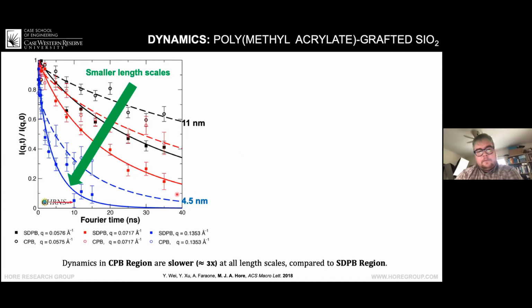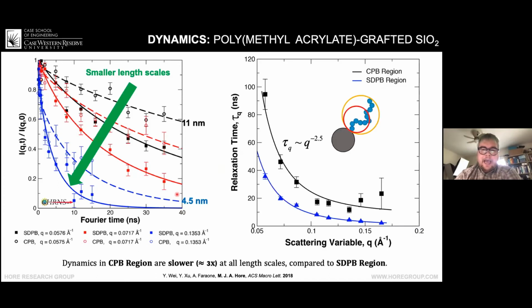So we can fit these data and we can tabulate what we observe, and we find that the relaxation times decay as Q to the minus 2.5, and all that's saying is that we get good agreement with the Zimm model. But more importantly, you see that even at local length scales out here, the concentrated region, the region that's more stretched, is relaxing more slowly than the unconfined region farther away by a factor of about 3. It's also worth noting this is on the order of a couple of Kuhn segments here. So even very locally, this effect persists.